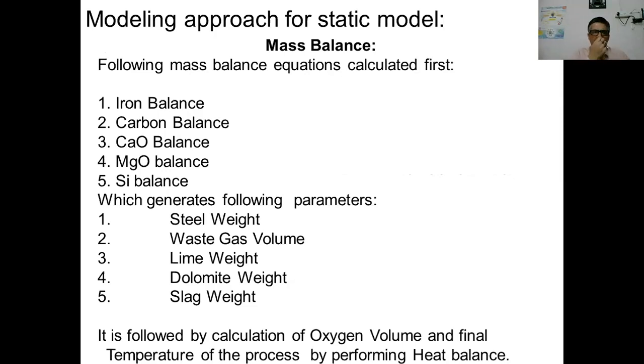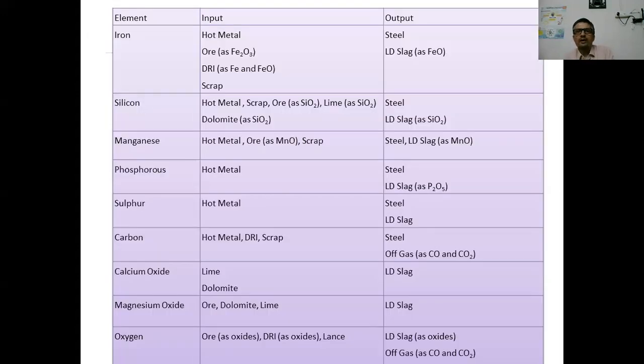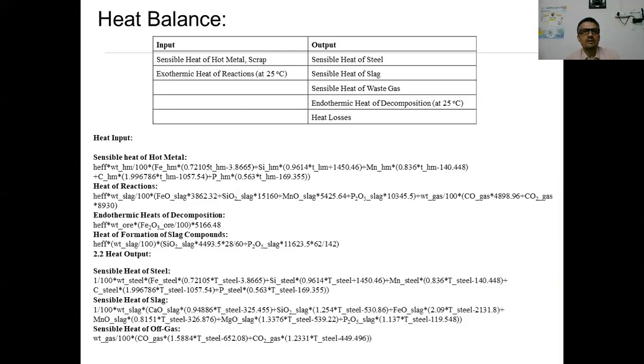In our calculation, we have performed the mass balance equations like iron balance, carbon balance, CaO balance, MgO balance, and silicon balance. These are all linear equations which are able to generate weight, waste gas volume, lime weight, dolomite weight, and slag weight. Having done this, it is followed by the calculation of oxygen volume and final temperature of the process by performing the oxygen balance and heat balance. For doing the mass balance, we must know the source of various elements. Iron is coming from hot metal, ore, and DRI scrap, and it is going out in the form of liquid steel, and in the LD slag in the form of FeO. Similarly, for all the elements, we can make a table, and then the equations can be set up for the heat balance.